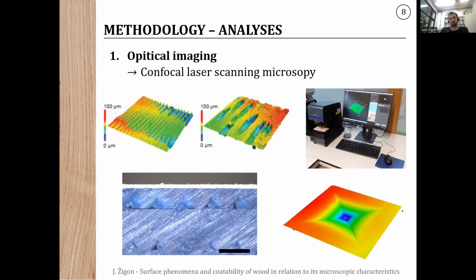Under optical imaging is also confocal laser scanning microscopy, which we do have at our department. Probably you know this technique. It's nice to use it for imaging the 3D structure of wood or any other surface. We can see two pictures of spruce wood and beech wood. Above, right below is some indentation on the coated wood with some other equipment. And on the left below, we see again an example of measuring the coating thickness on a 3D printed material.